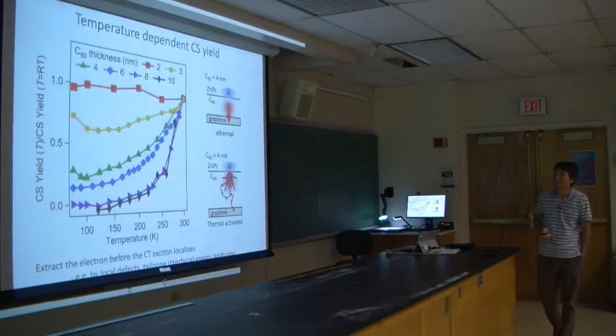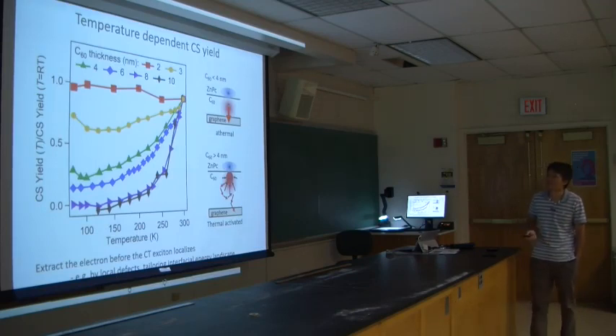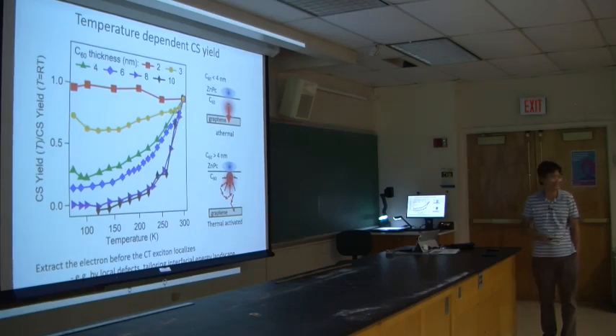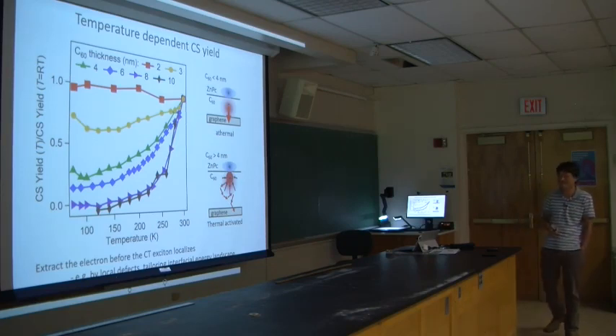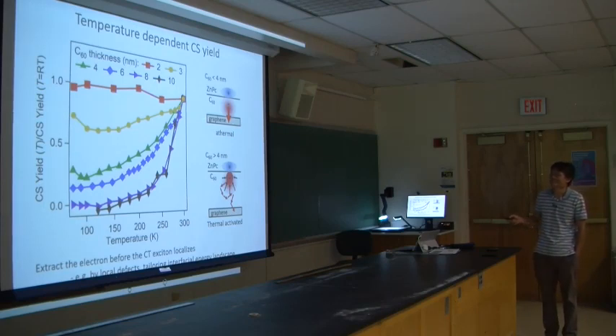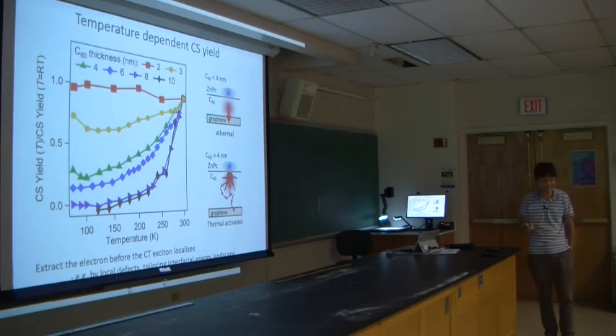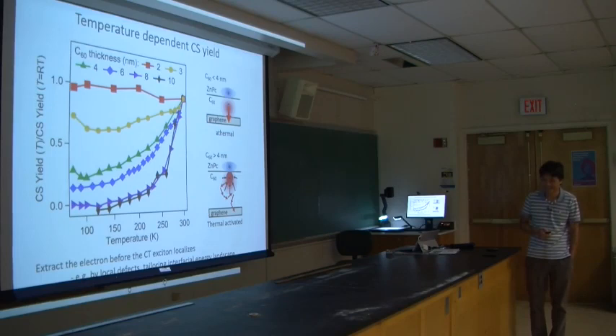layer. So we also did the temperature dependencies. This delocalized state basically doesn't depend on temperature. The localized one has a strong temperature dependence, probably due to some thermally activated process, right? So now, of course, you can engineer another type of acceptor within this kind of distance from the interface, right? But it's difficult to do it that way.